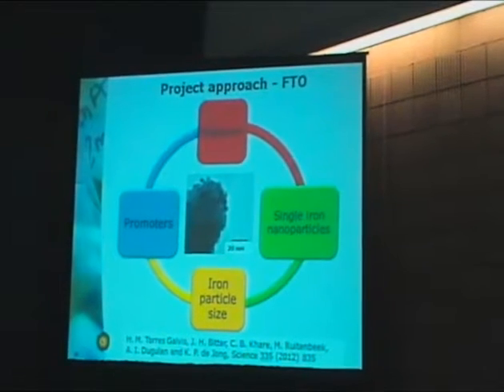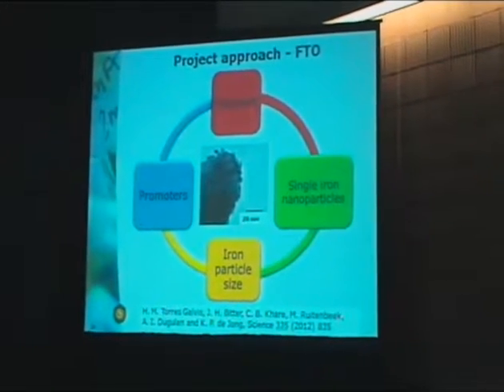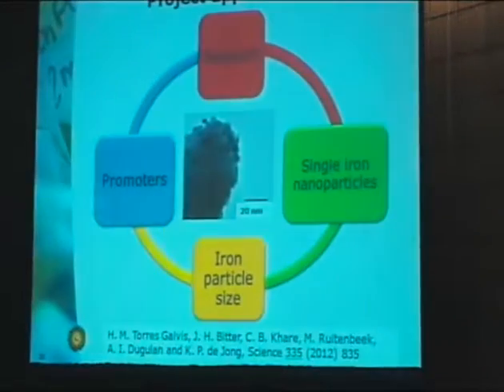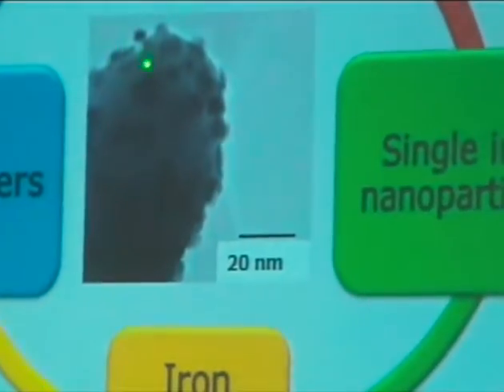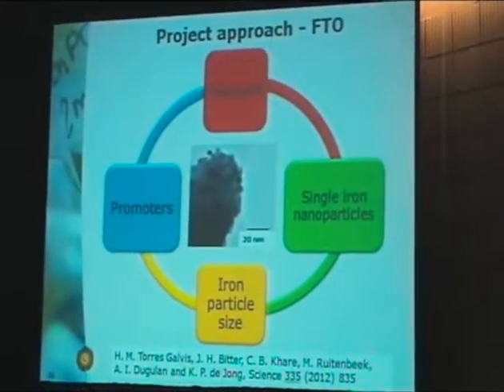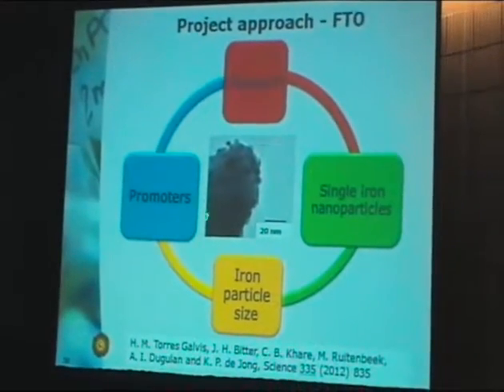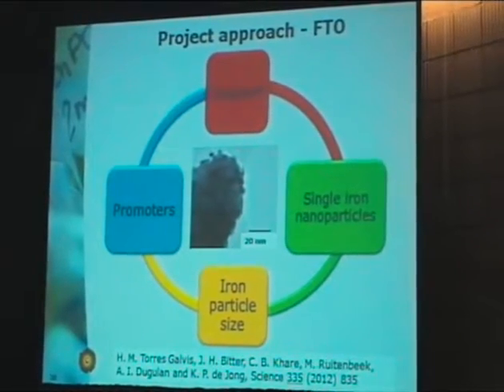It's a long story, and I've only 5 minutes to go, so I'll summarize it by saying that it's an integrated approach by the support selection, the fact that we must prevent aggregation of the iron nanoparticles. I will highlight this point in particular. Control the iron particle size, but also the promoters. And this ends up in a catalyst where we have an alpha alumina particle of, let's say, 100 nanometers or more, and we have iron nanoparticles of 10 to 20 nanometers dispersed over the alpha alumina. The iron particles are promoted by sodium and sulfur. I won't go into that, but those promoters are essentially to suppress the methane formation at the elevated temperatures that we apply. And to first then discuss the support effect, then the size effect, and then the aggregation.